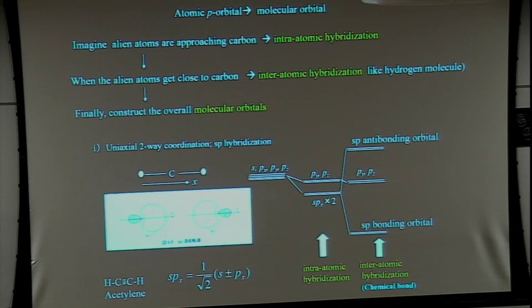So in the first step, the intra-atomic hybridization occurs. Intra-atomic hybridization means the sp hybridization, but the py and pz are not so strongly affected here. When the neighboring atoms get closer and closer to the carbon, some chemical bonding occurs. The chemical bonding is exactly the same as the formation of hydrogen molecules: bonding and anti-bonding. That is the chemical bonding around the carbon atoms.